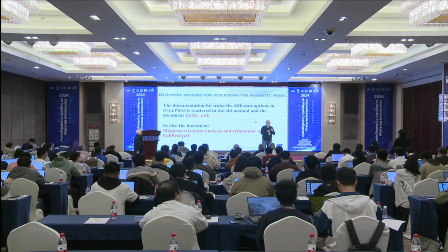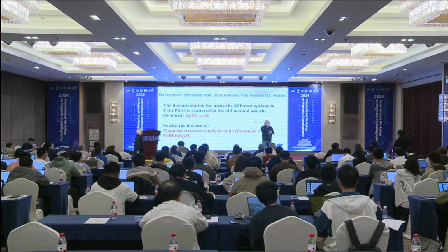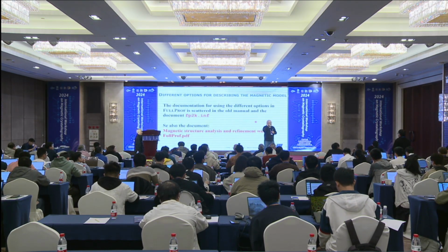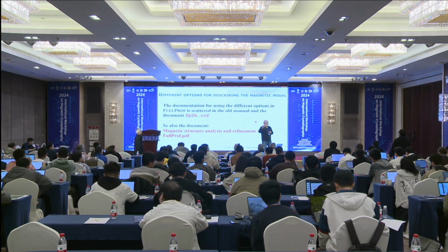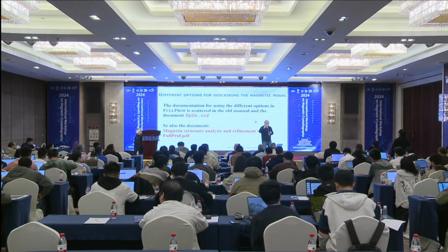So if it is equivalent, should I put -1? For example, suppose that you have a primitive cell and you have a propagation vector 0, 0, 0.23, you have to put -1 and write only 0, 0, 0.23.